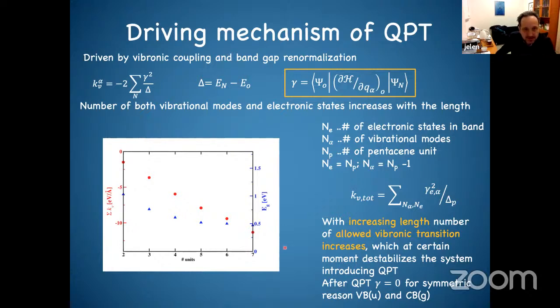It's increasing because I also have more vibrational states. So the sum is over these bands, which contribute, but also over the vibrational modes. At one moment, this vibrational coupling gets stronger and stronger. Then the system collapses, and these two levels exchange, and the vibronic effect due to this vibration becomes zero, because now I have a conduction and valence band which are of the same symmetry but opposite. So there is no longer instability here.